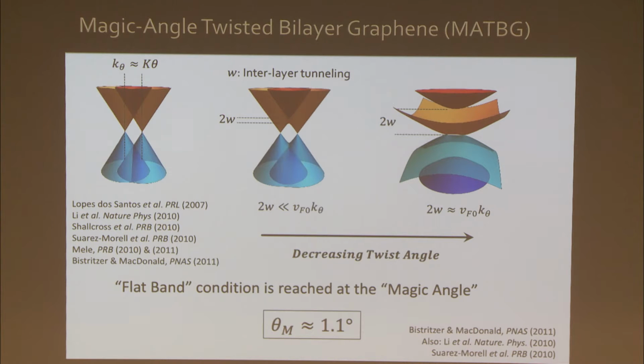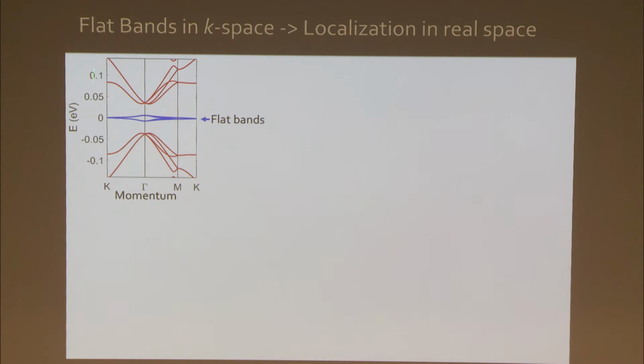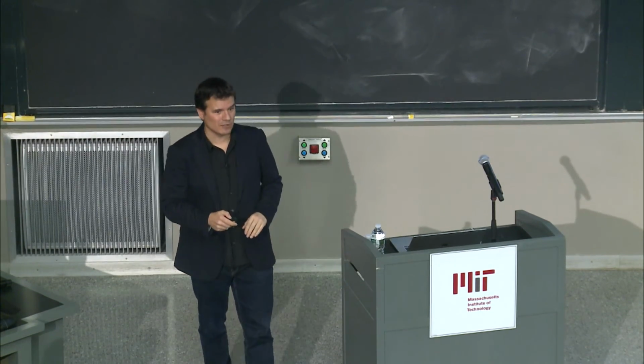Now, this is a cartoon picture. Let me show you an actual calculation. This is energy versus momentum for magic angle twisted bilayer graphene. These blue bands are the flat bands. You can see that they're not exactly flat. They're not all at 0, but this is much, much flatter and very different from the original Dirac cone that I showed a moment ago.